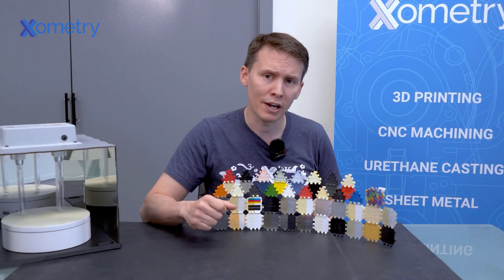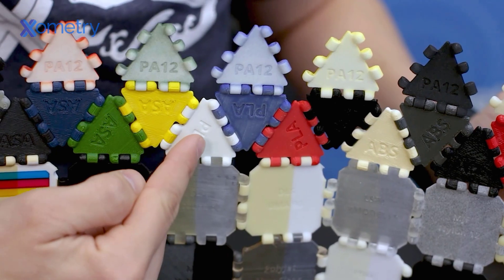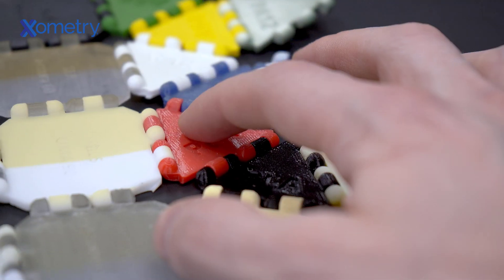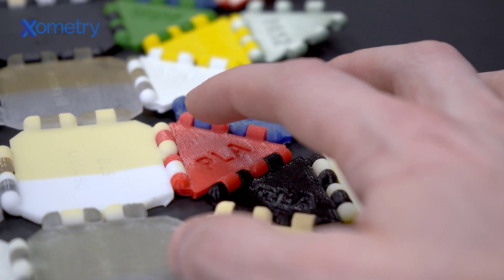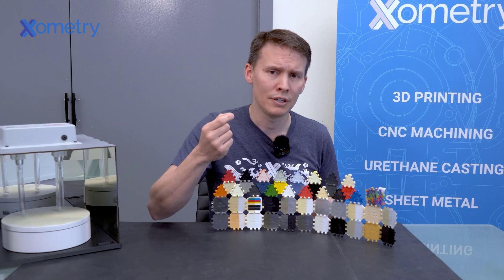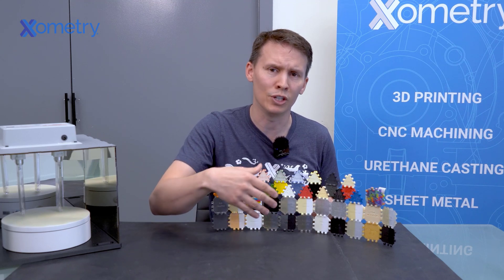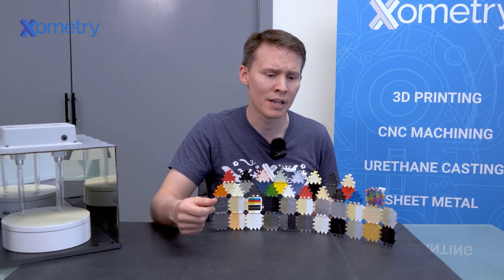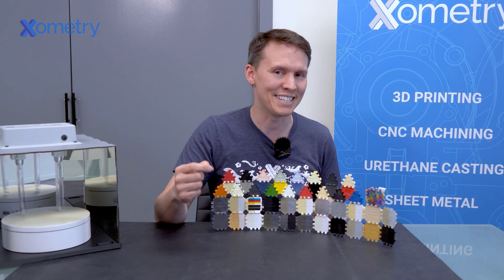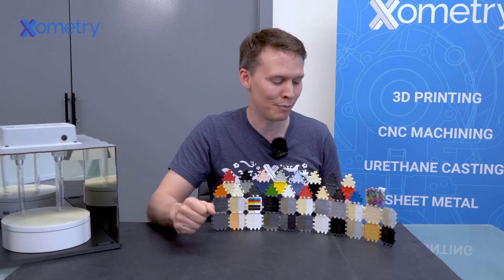I was very surprised at how PLA, a desktop 3D printing material, survived this test. But something really strange about all the PLAs is it's tacky to the touch. It feels sticky. And I'm actually not sure why that happened. But out of all these materials there, this is the only one that had a tactile change. And it's also something that I can smell. It smells like a desktop 3D printer right now as I'm doing this video.